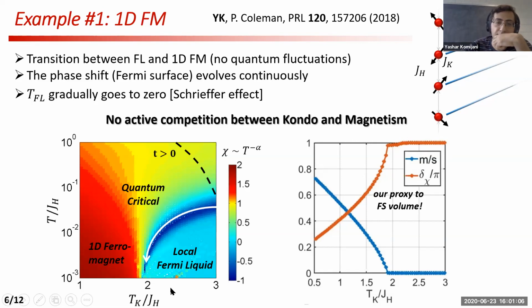And this is the phase diagram extracted from the susceptibility, and you can see that there is this local Fermi liquid phase, and this is the 1D ferromagnet, and there is this quantum critical regime in between. What is interesting is that the Kondo temperature gradually goes down to 0. So close to the quantum critical point, the Kondo is weak because the Kondo temperature is weak. Magnetization is also weak. And so I would argue that in this case, there is no active competition between Kondo and magnetism. Okay. Now, is there any question about this part? I would move to the second example.